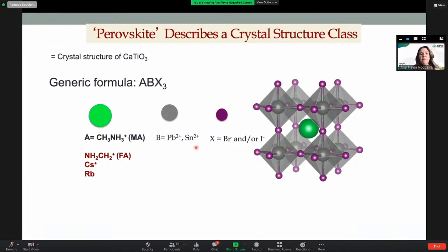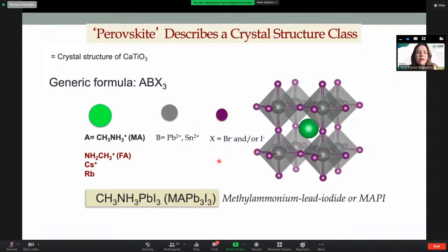In the B site, this is a different cation. In most cases you have lead, but there are also many studies involving tin. And the halide makes the difference here because the X is a halide, which can be bromide or iodide. In the perovskite used for water splitting, we have oxide on the X site. Okay, so these are specific compositions for photovoltaics. MAPI is the perovskite, the first one to be studied. I think most of the papers are focused on MAPI. It is methylammonium lead iodide. You see here that in the A site, we have only an organic cation.